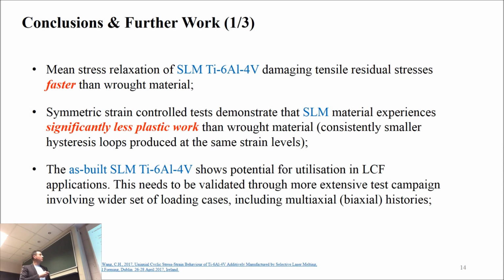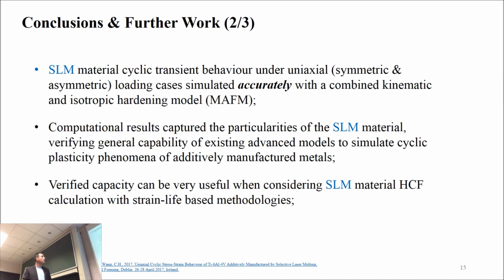In conclusion, as I mentioned, the mean stress relaxation is happening faster for the SLM material. Less plastic work happens on the SLM material, so it means that it is much less ductile, and this goes back to the microstructure. This is something that needs more investigation, but from our investigation so far, it means that we have the potential to utilize this material for LCF applications, for low cycle fatigue applications, if defects are not present. And this is something that we almost always get out of the SLM process. The transient behavior under cyclic loading can be simulated accurately with the models we have tested, and this can be very useful for high cycle fatigue calculation, where strain-based methodologies are used.